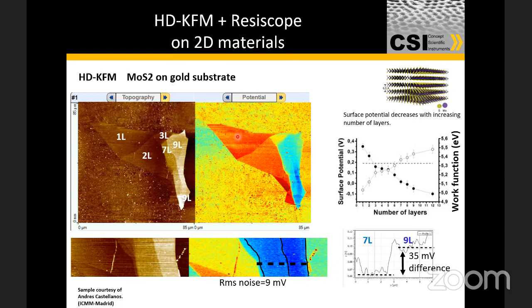When you come down to the potential image, the redder you get means that this region, in this particular case on this MoS2, has higher surface potential compared to the background, that is the gold substrate, and that is what is represented on this graph here. You see the background, all the yellowish bits, are at this potential, and the red bits are at the higher potential. That's essentially what we are trying to show with the color coding here. So the color coding, in a certain sense, is the intensity of any functional measurement of the surface. So X and Y, and the color represents the voltage response, which translates into surface potential differences, depending on what image you're measuring.